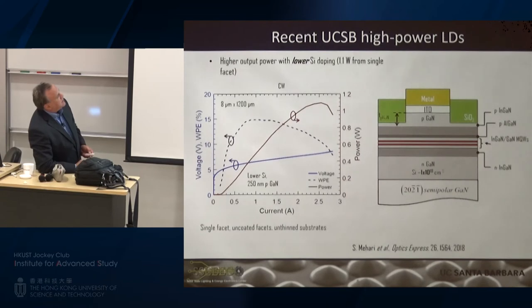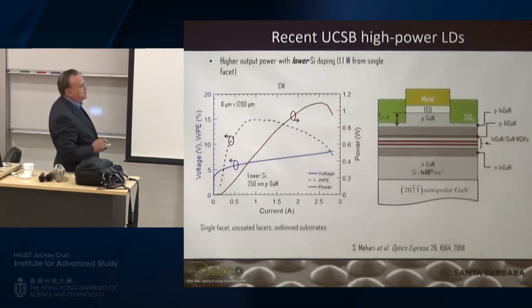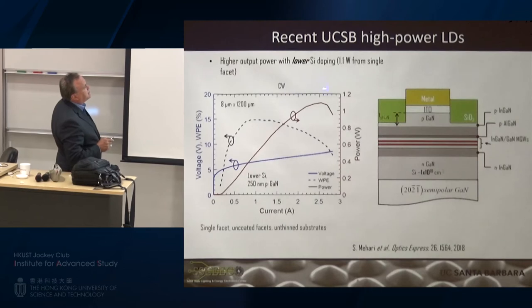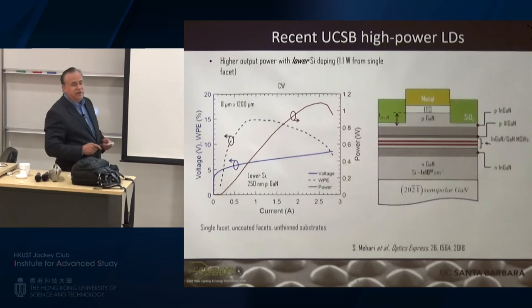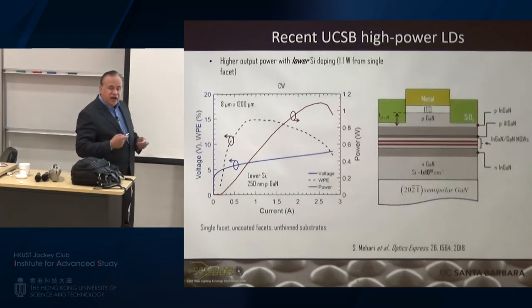So here's one of those single chips. This is one of the first versions we did at the university, where we basically go with gallium nitride. The difference between a laser and an LED is that our lasers are edge emitting, and we get confinement by etching a ridge here in the p-gallium nitride, putting silicon dioxide around it. Then instead of using metal directly on the p-GaN, we found it was necessary to use ITO here, a very thick ITO layer. And ITO being transparent is a much better waveguide material to confine the light here. That was one of the key breakthroughs in getting to high laser powers.